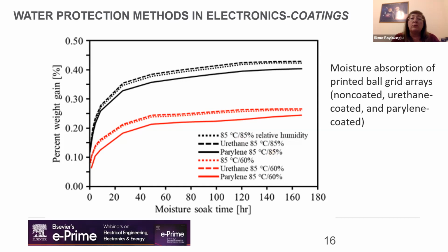But of course, we need to decide whether we need conformal coating or not. Although conformal coating does not completely protect against water, it is still used because of its insulation benefit by allowing reduction in conductor spacing, protection against chemical and corrosive attack, and by providing mechanical support and vibration resistance. Of course, when you have repair issues with conformal coating, you get much more trouble removing the conformal coating, and you need maybe extra work to repair the devices.